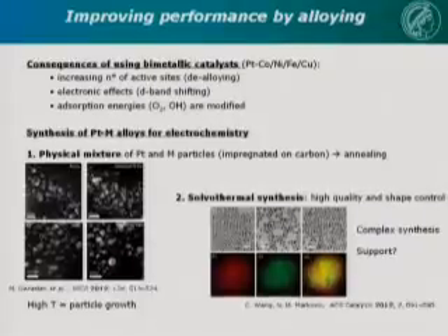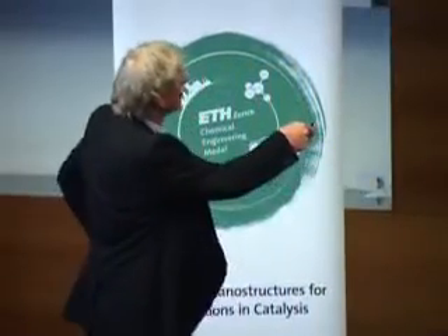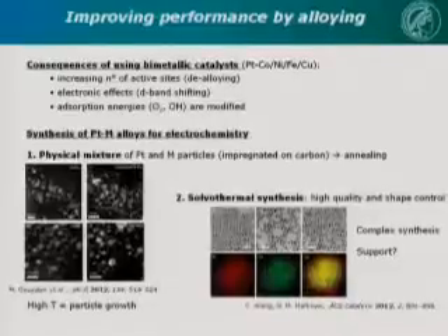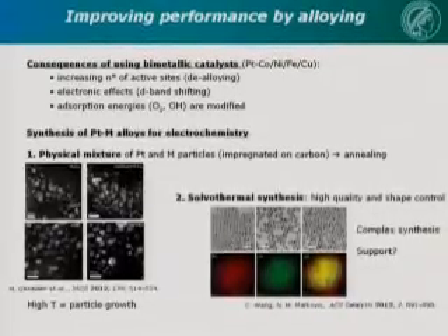For alloying, we typically need high temperatures. So here, for instance, we have platinum and platinum-cobalt alloy in this case. If you heat that to high temperatures, you get a nice homogeneous alloy. But if you heat it to high temperatures, you also get growth of particles. And that leads to reduction of the activity. You don't want big particles.